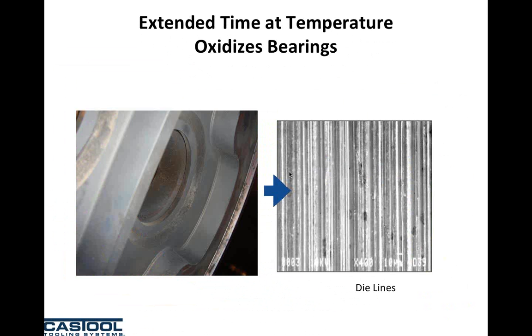So you can see on the left-hand side, the bearing is oxidized. And on your right-hand side, looking at the profile, you can clearly see the die lines because of the oxidized bearings. And there is no way you were able to put nitrogen in the oven to get rid of oxidation, because you only need a very minimal amount of oxygen to do the damage.